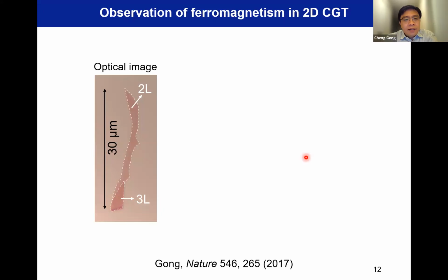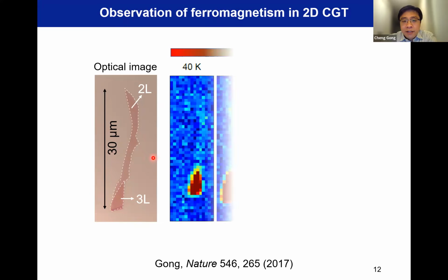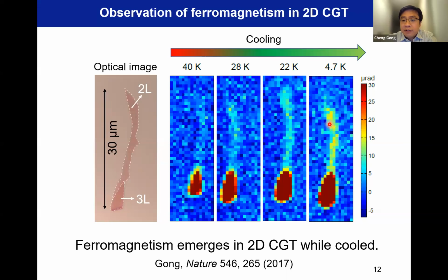So this is atomically thin CGT exfoliated on silicon oxide and silicon, and when you put this into the cryostat to cool down, you can see there is a clear emergence of a Kerr rotation angle here for the 2-layer region.